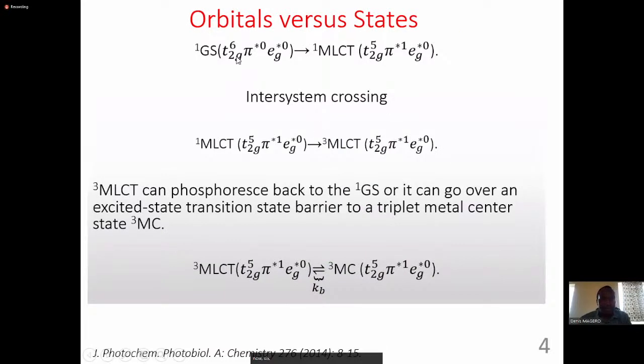As explained previously, from the singlet ground state to the singlet metal ligand charge transfer, there's intersystem crossing. Then you go to the triplet metal ligand charge transfer. If you cross the barrier, then there's a barrier here that we're interested in, to be able to calculate the luminescence lifetimes.